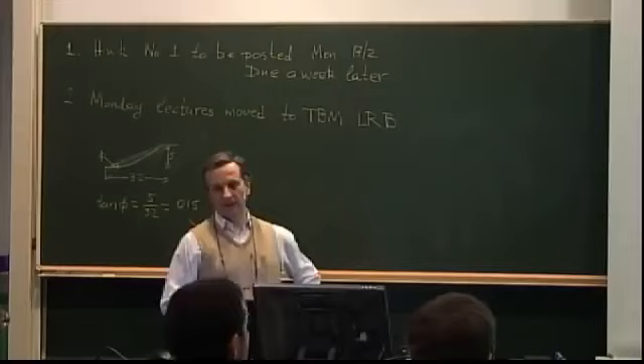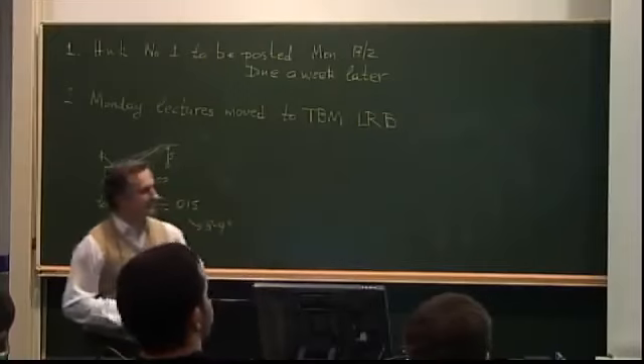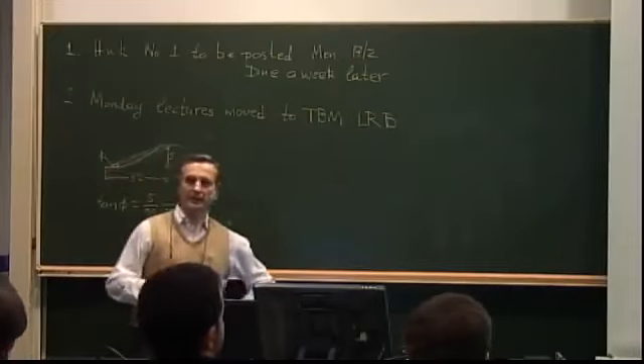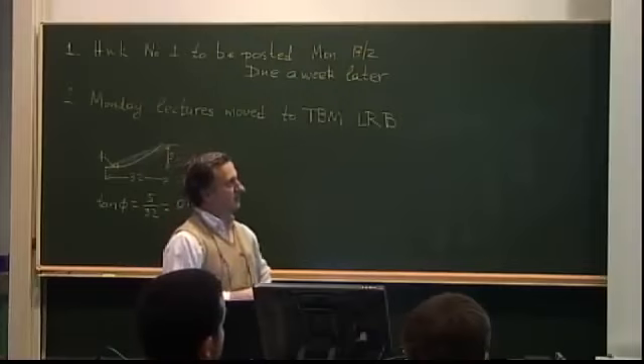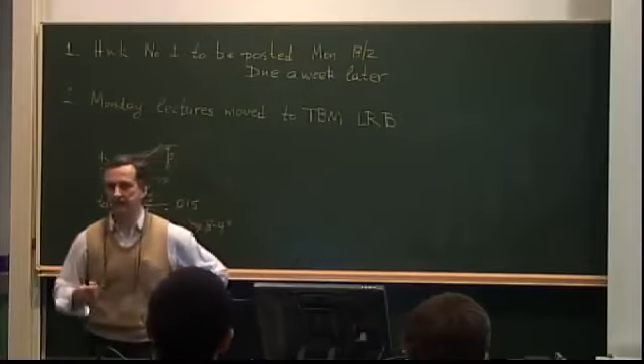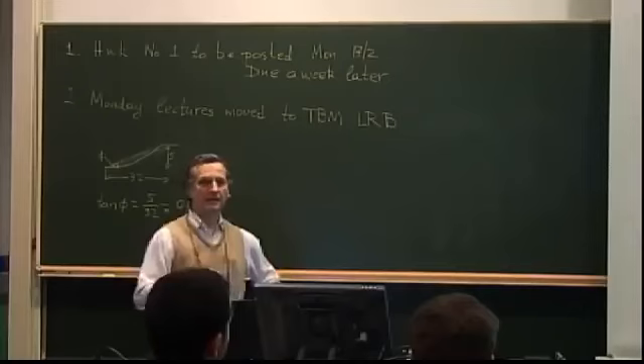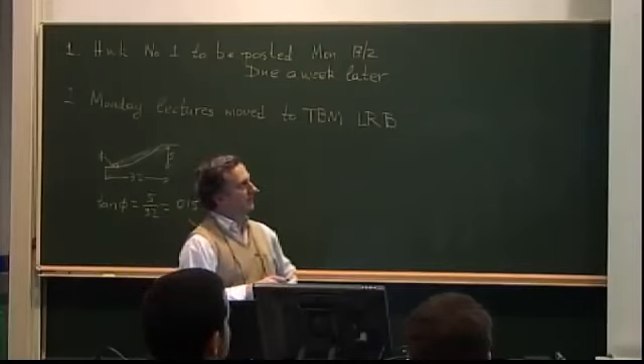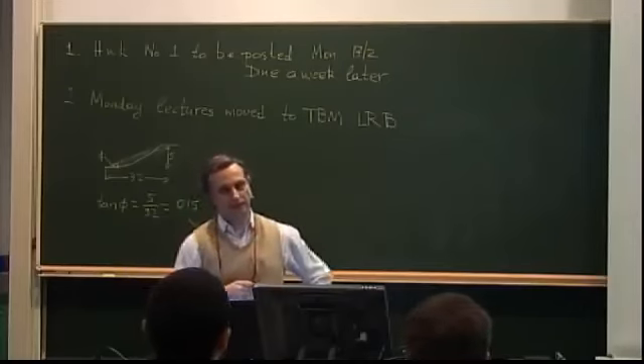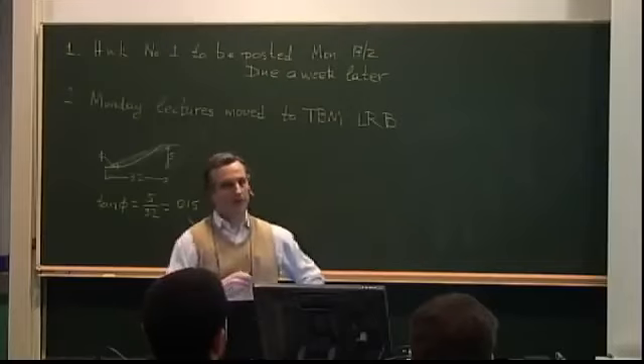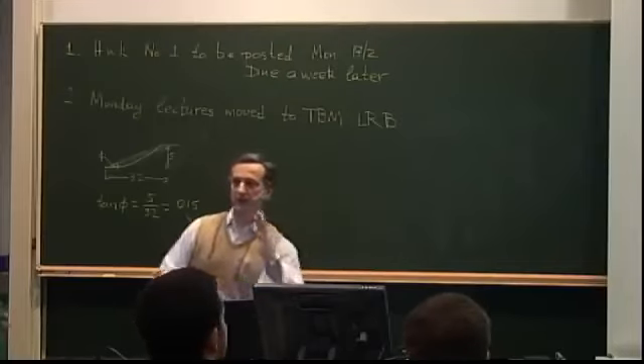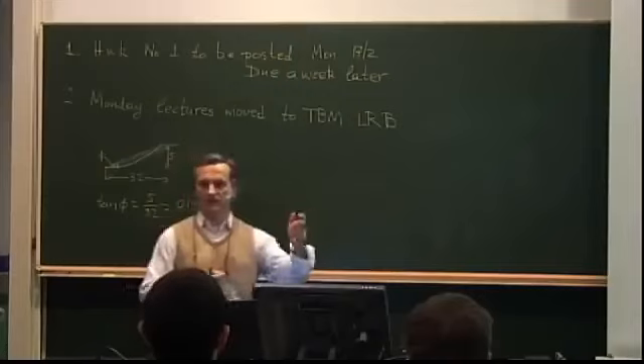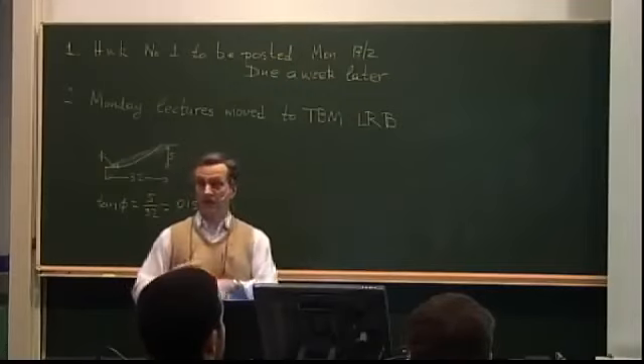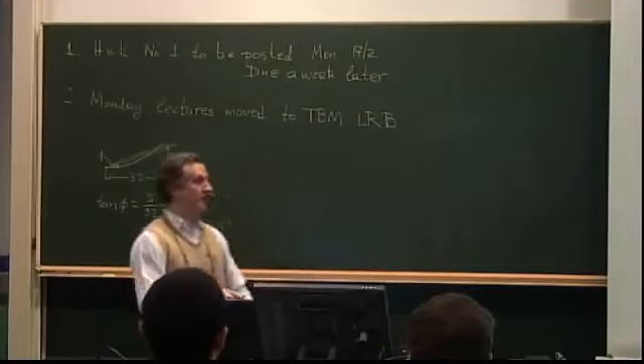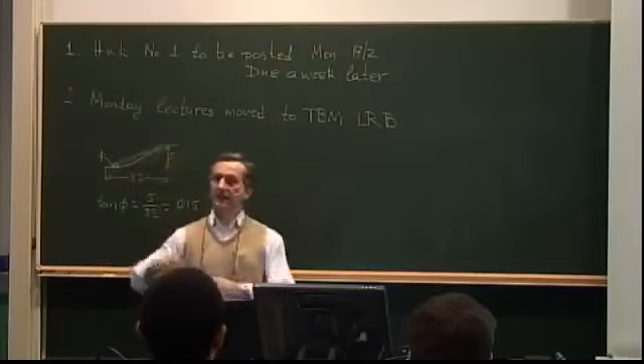and the Hoffman criterion. And interestingly, in most cases, the predictions have nothing to do with what happens in reality. Even though the criteria seem to agree, in reality, the plus theta plies will develop a crack, a matrix crack first, which is a transverse failure. Then you get a delamination between the plus theta and the minus theta, which none of these criteria can predict, and then you get final failure.